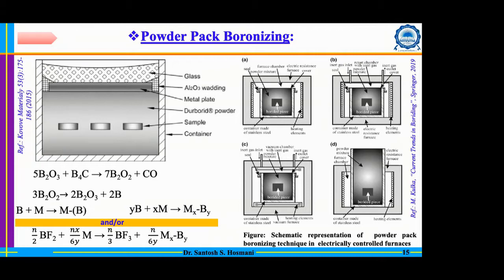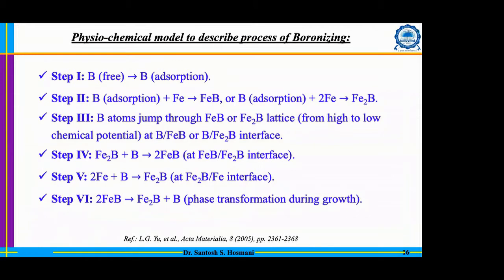So you can fill that chamber with inert atmosphere, or even use vacuum. Your container can even be a longer container, with only a limited portion of it exposed to the elevated temperature. That means even if you have a shaft type of component, and you want boronizing on only a limited region of that shaft, that is also possible, because only the heated region should be exposed there. Chemical reactions will occur wherever the temperature is sufficiently high, and only then will boron potential be generated. Otherwise, it will not be generated. That means selected regions can also be successfully boronized in this pack method. The only thing is that you have to alter the design. So now, basically, there are well-known 5 to 6 steps in this boronizing process in the physicochemical model.